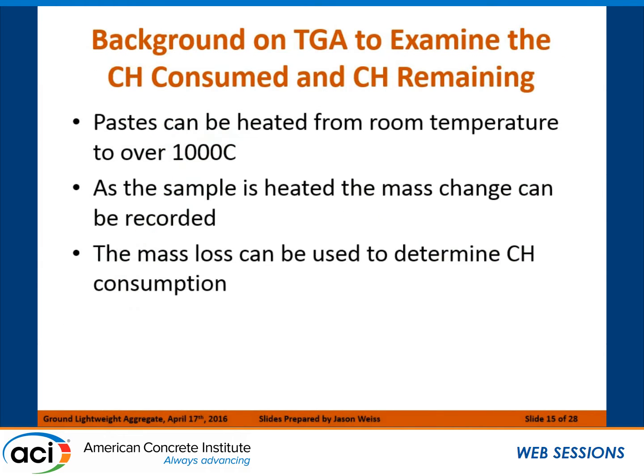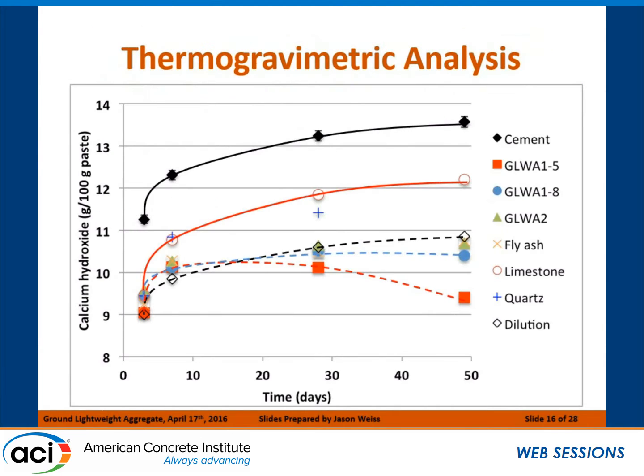The other thing that we could do is we could actually start to bring in thermogravimetric analysis, where all of a sudden now we can take these pastes and heat the hydrated paste from 100 degrees to 1,000 degrees, and we can essentially measure the mass change and use this to determine the amount of calcium hydroxide that's being consumed. The amount of calcium hydroxide that's being consumed would give us a great indicator of how pozzolanic that particular material is. So when we start to do that, we start getting plots like this, which may cause you to have a headache or may cause you to say, wow, that's even more confusing than I thought it was. But let's just walk through here.